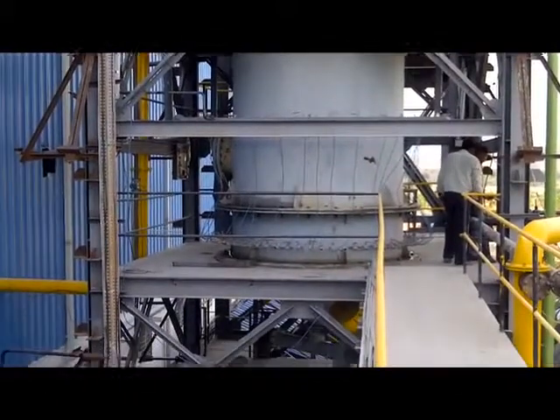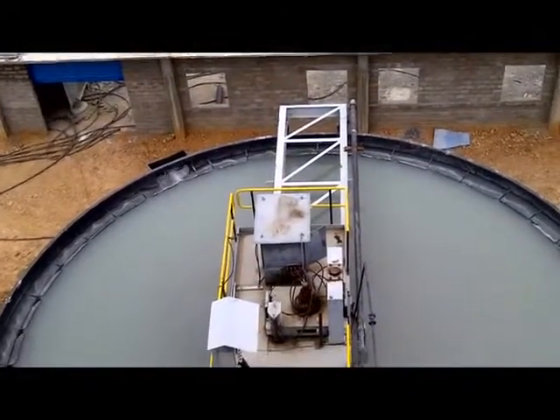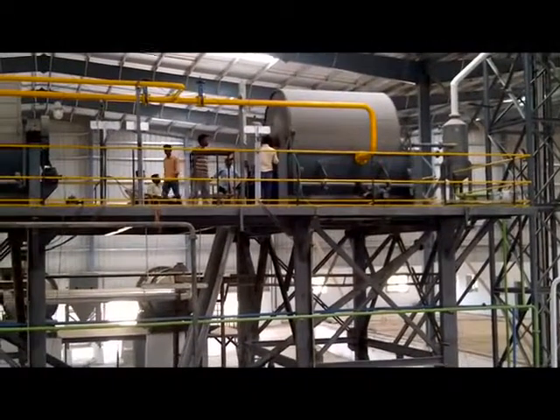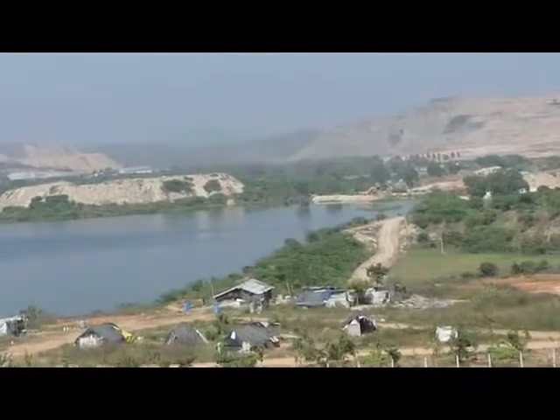The discharge from the bottom of the column containing barite concentrate is sent to the high-rate thickener, and the underflow of the thickener is sent to the drum filter for dewatering. The unwanted silica and/or gangue is carried into the froth phase, overflows into the launder and is further discarded to the tailing ponds. In the flotation process, froth phase plays a vital role to collect the particles and to provide the desired separation. It is of paramount importance to maintain a stable, uniform and free-flowing froth.